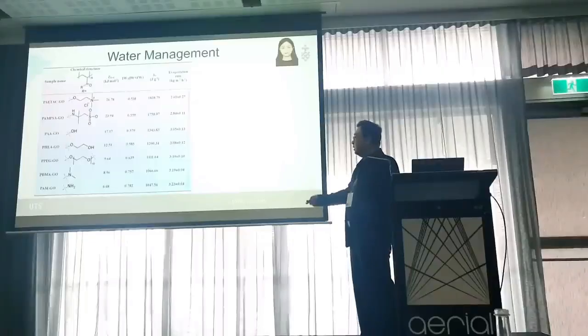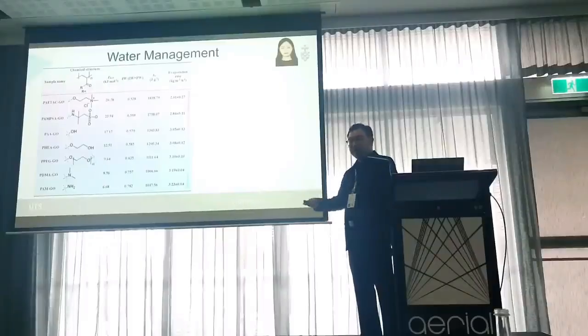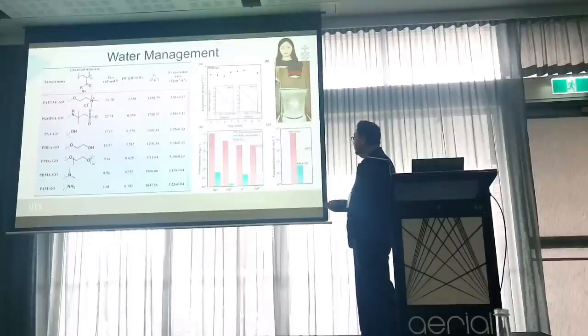So we tested the evaporation performance as expected. This hydrogel shows the highest water evaporation because it has a high content of intermediate water. And then we did a second test with seawater, and we observed that the salt concentration is very low, similar to distilled water.